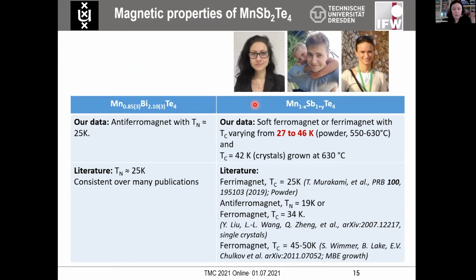Well, what are the consequences of that? The consequence is a much larger variety of what is observed for the magnetic properties. So as I said, here in bismuth, everybody reached consensus. It's an antiferromagnet. Here with MST, there is everything possible. So there are now reports that tell you it is antiferromagnetic. There are reports with ferri or ferromagnetic ordering in this phase with very different critical temperatures. And our own data, dependent on how we obtain our powders or crystals, also shows that we are dealing with a ferro or ferrimagnet with a very varying temperature of the magnetic transition.